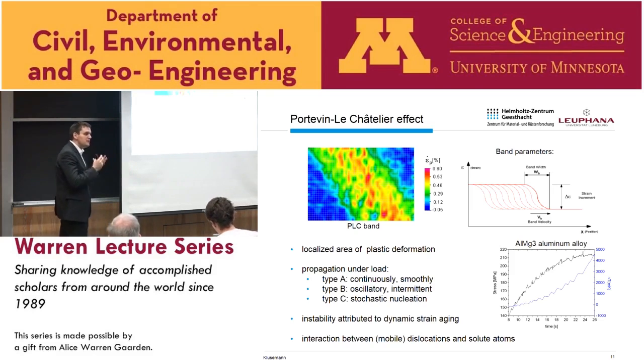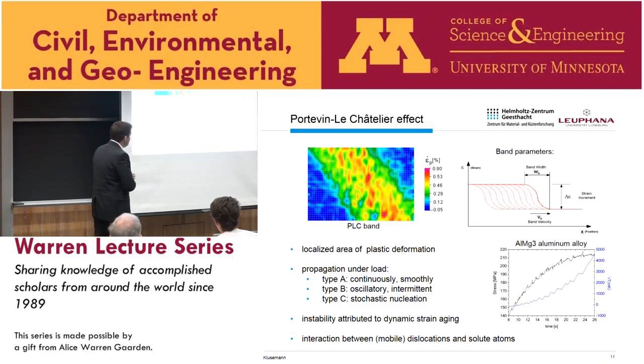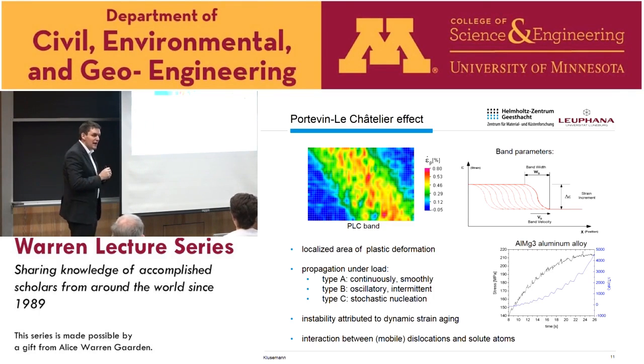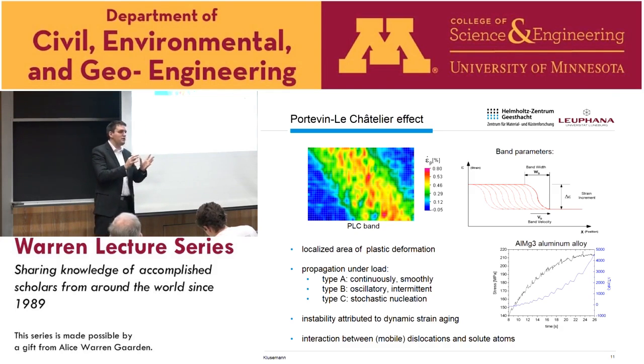Okay, so by that I will go to the next topic, which is the so-called Portevin-Le Chatelier effect. The Portevin-Le Chatelier effect is a kind of material instability which is related, of course, also to dislocations. You can in principle imagine it in a way that you have a pure alloy in the beginning, and of course you want to strengthen the properties, so you have additional alloy elements in it, in this case magnesium, and this might lead in specific regions of strain rate and temperature to some local instabilities, which then result in these so-called Portevin-Le Chatelier effects, or bands.